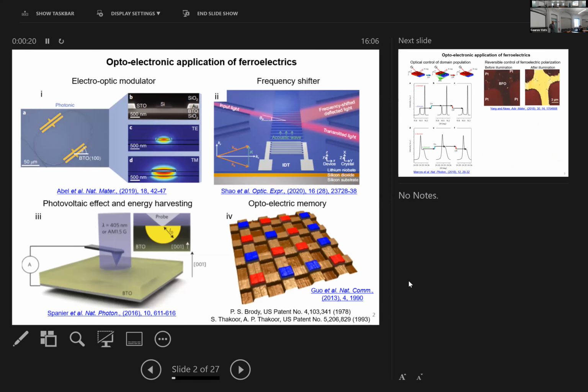For example, in this first one, electro-optic modulators using ferroelectrics have been demonstrated. So here they apply electric field using these gold pads, and because of that, the domain population in this barium titanate layer changes. And as a result, the light modulates in this silicon waveguide, which is just above it. Another application is this optical frequency shifter. So basically, they made these IDTs which generate surface acoustic waves through these ferroelectrics, and this was used to modulate light, which was coming from here.